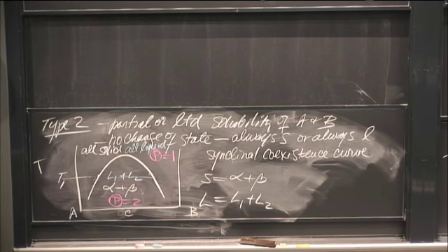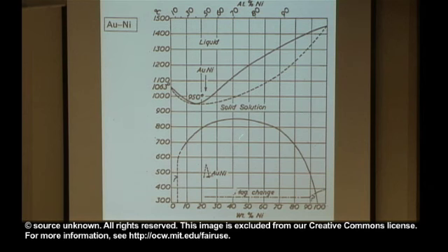All right, so let's look at some examples. Oh, here's this one, actually. That's why I had it. If you go to lower temperature, gold, nickel, look. They actually phase separate. That's shocking. I always find this one shocking, because you think gold, nickel, nice FCC metals, they should substitute for one another. Look what happens. If you start putting nickel into pure gold at 700 degrees, you get to 10 weight percent. You put any more in, boom, right across here. So this is going to be two-phase.